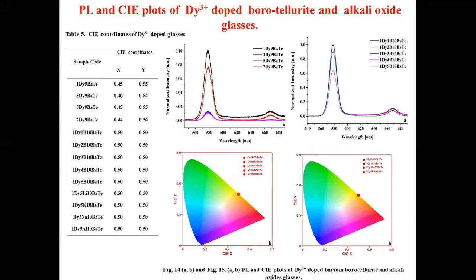These are for the dysprosium doped samples, and they emit yellow light, and the maximum intensity of photoluminescence is around 580 nanometers. So that is yellow light. So dysprosium doped samples in the barium borotellurite system are a yellow light emitter.